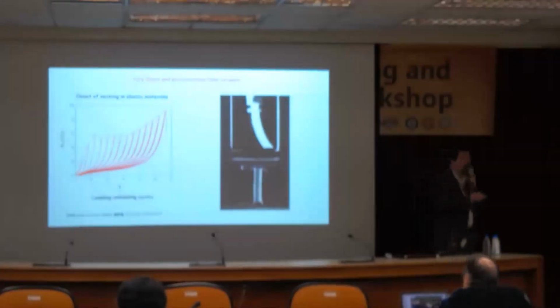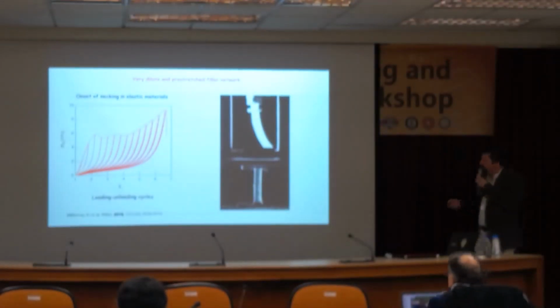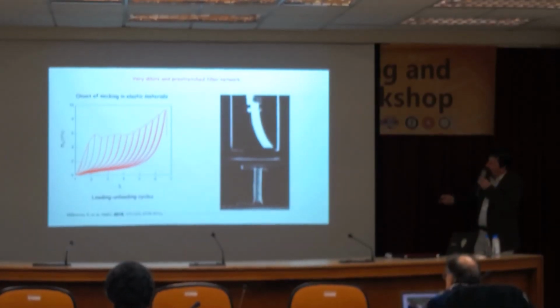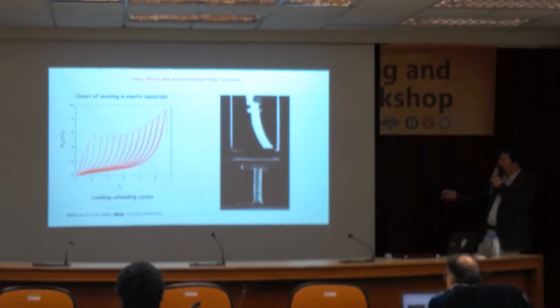I told you before that we can also detect bond breakage. This is maybe more interesting and more original. And here I'm going to show you an example related to fracture. So this is stress strain of a material. These are loading, unloading curves. And you can see that there's actually no residual deformation. So this is an elastic material that shows some sort of plateau, some yielding.